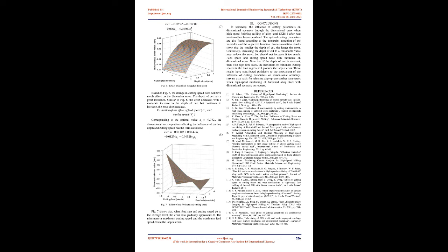the error also increases. Evaluation of the effect of feed speed, f, and cutting speed, v, corresponding to the optimal value x1 = -0.772, the dimensional error equation reflecting the influence of feed speed and cutting speed has the form as follows: error = -0.01107 + 0.01425x2 (8), -0.01234x3 + 0.01521x2x3, Fig 7. Effect of the feed rate and cutting speed. Fig 7 shows that when feed rate and cutting speed go to the average level, the error also gradually approaches zero. The minimum or maximum cutting speed and the maximum feed speed create the largest error.